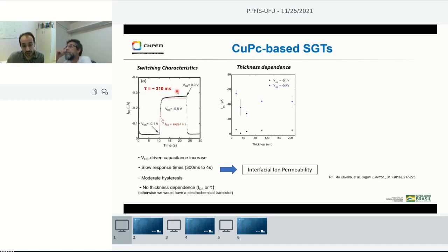We also found this a bit suspicious. Then we realized, by reading the literature, that for cases where you have moderate hysteresis, slow switching times, and capacitance that varies with the increase of the DC voltage, we may have some ion doping.